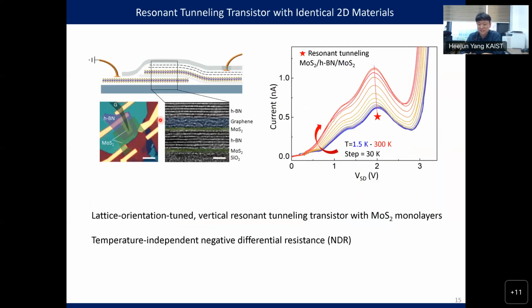Okay, so the first experimental result from our group is like this. We made monolayer MoS2, and here we have a 2D insulator, hBN, hexagonal boron nitride. The interesting thing is that these two MoS2 monolayers were from one single body. This is called the tear-and-stack method. We tear one MoS2 flake, keep the orientation of the lattice, and make this stacking. So the unique thing here is that the lattice orientations of the two MoS2 layers are well aligned.